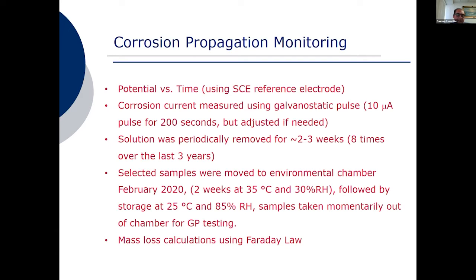And the solution was periodically removed for about 2 or 3 weeks at a time. And this was done about 8 to 9 times over the last 3 years. This is to allow additional oxygen to penetrate into the concrete. Most of the samples are kept in a high humidity environment, greater than 85% relative humidity.